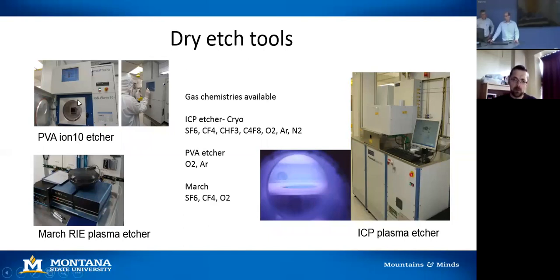And you also need to remove the photoresist and sometimes clean up some polymers. So we have this case, a microwave plasma etcher. It has oxygen argon in it, and it's just for removing photoresist or other polymers. We have a March plasma etcher, which is a parallel plate etcher. It has gases for silicon oxide, silicon nitride, and oxygen for, again, etching polymers or activating surfaces for bonding.